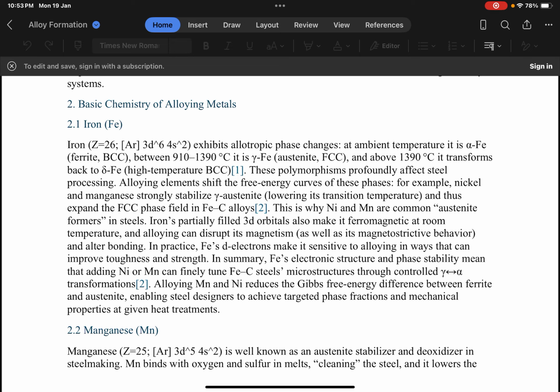This phase transformation is extremely important in steel processing, allowing elements such as nickel and manganese to stabilize the austenite phase, meaning they allow the face-centered cubic structure to exist at lower temperature. Iron also contains partially filled 3d orbitals which make it magnetically active. When alloyed, these electronic interactions change, affecting mechanical strength, toughness, and magnetic properties. In short, iron's phase flexibility allows engineers to control microstructure using heat treatment and alloying.